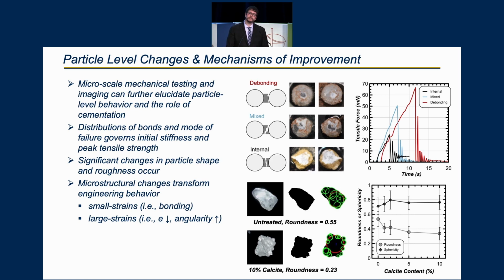Post-shearing, we can see significant changes in particle shape and roughness afforded by the cladding of those particles with precipitation, and these persist even at larger strains. Direct imaging of those particles can afford quantification of these changes using various metrics, such as sphericity and roundness, such as that shown here in the plot with changes in cementation level. The net result, of course, is the transformation of behaviors at small strains, primarily resulting from particle-to-particle bonding, and at large strains resulting from the soil matrix, which is now densified and has particles that are more angular.